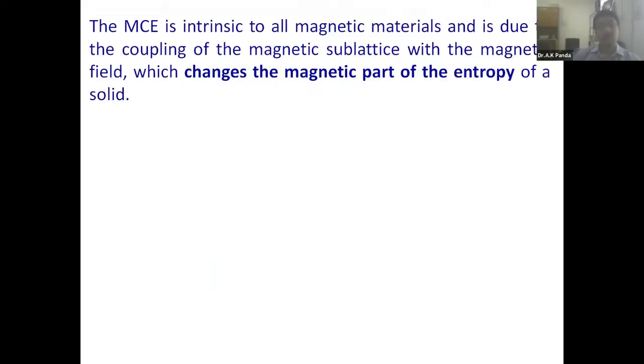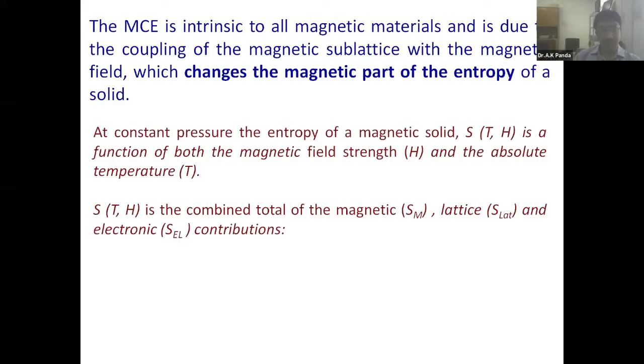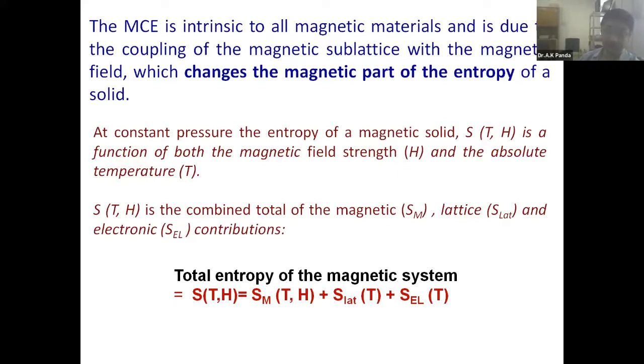Basically, you know that it is intrinsic to any magnetic properties, and there is a magnetic lattice, and that is due to the coupling of the magnetic sublattice with the magnetic field, which changes the magnetic part of the entropy. Now, two things are very important: the entropy of the magnetic solid is a function of temperature and field, in fact the magnetic field strength. And secondly, it is a combination. The entropy is a combination of magnetic entropy, lattice entropy, and the electronic entropy.